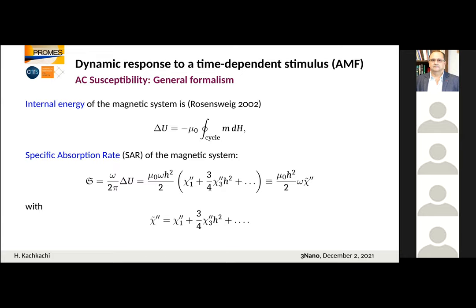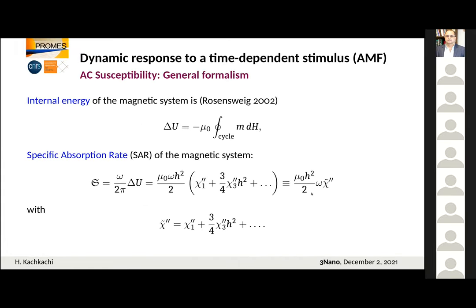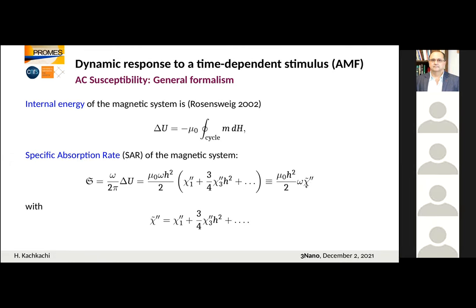So if we want to compute this specific absorption rate, which is the heat power dissipated in the magnetic system divided by the mass of the magnetic substance, roughly the heat power per unit mass, we need to compute the AC susceptibility, which, as is well known, is related to the absorption. But this is the problem. The crux of the problem is to compute this AC susceptibility, which is the dynamical response of the complicated magnetic system.